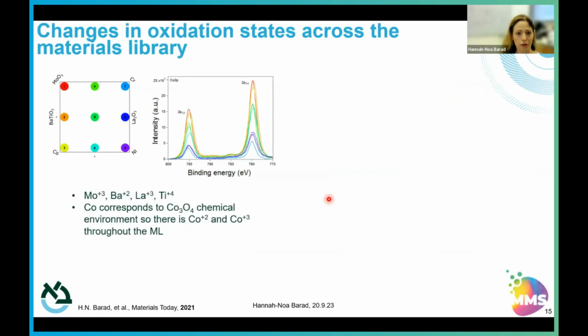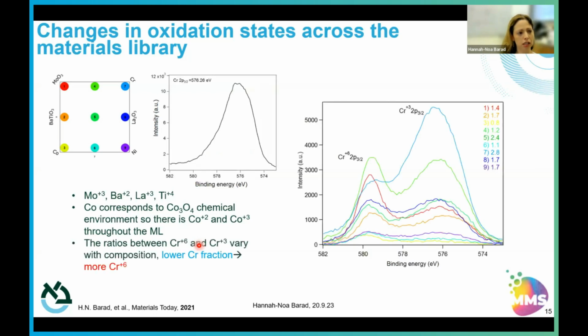Of course, we also, for the sake of catalysis, wanted to investigate the different properties of this library. So I'm just going to give you one example of the things we looked into, and this is oxidation states, which are, of course, very critical. So for some of the elements, we get the standard stable oxidation states. For others, we get two stable oxidation states, but well known, so similar maybe in the cobalt to the Co3O4 phase. What we do see that's very interesting is in the case of chromium, we have actually a gradient that goes between chromium +6 and chromium +3.